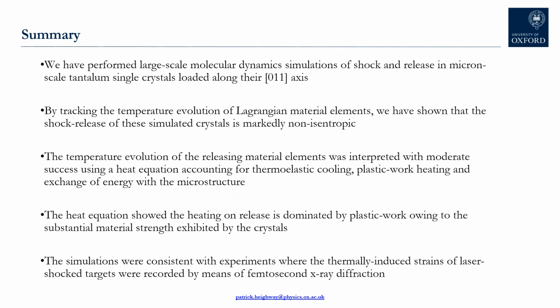To summarise then, we've simulated the shock release of micron scale tantalum crystals via molecular dynamics and found that the temperature following release greatly exceeds that expected from an isentropic release. We identified plastic work as being the culprit, which is owed to the high shear strain state the crystal assumes during shock release. And the same excessive release temperature was also observed in laser compressed foils using in situ X-ray diffraction via measurements of the thermally induced elastic strains following shock breakout.